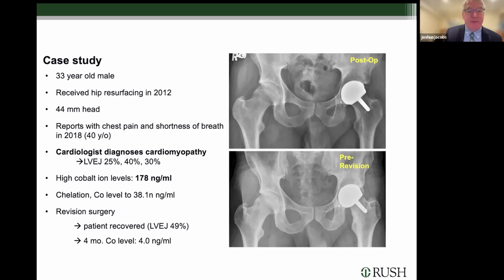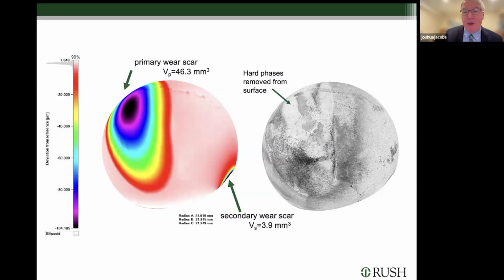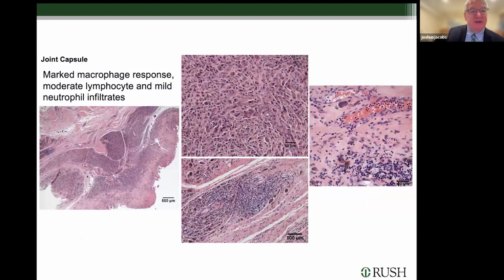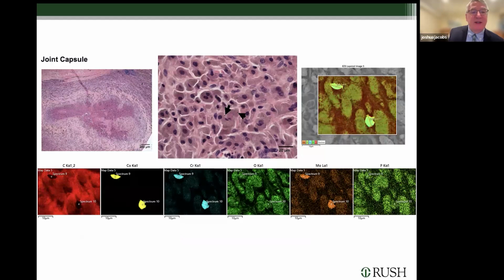The cobalt levels went back toward normal. You can see 4 parts per billion, and his heart recovered. You can see his ejection fraction is far greater after this. So this is real cobalt cardiomyopathy. On the retrieved implant, you can see this edge loading wear pattern showing a high wear situation, and the histology reveals some particulates in the tissue and an inflammatory reaction consisting of moderate lymphocytes and neutrophilic infiltration. In the joint capsule, you can actually see cobalt chrome debris.